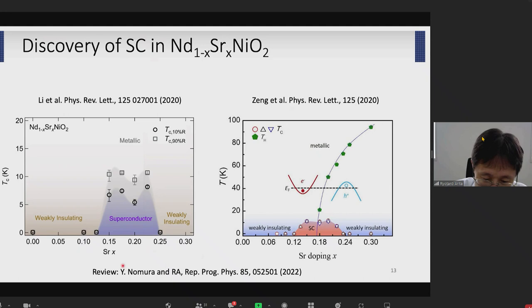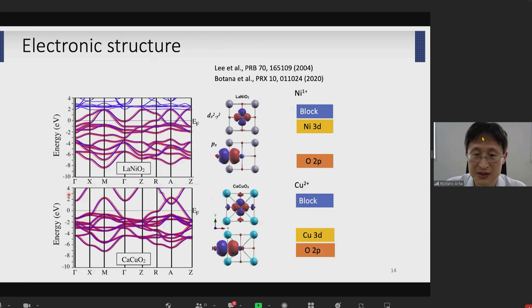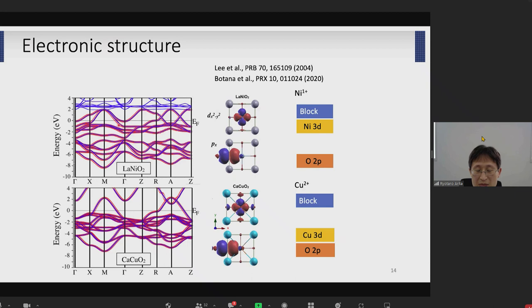This is the phase diagram — we see there is a superconducting phase. This material is now studied very extensively. Recently, Yusuke and I wrote a review paper on this material — please check it if you're interested. It is interesting to compare nickelate superconductors and high-TC cuprate superconductors. One common feature is that the nickel 3D dx²-y² or copper dx²-y² band makes a very large Fermi surface and is very two-dimensional — this band can be modeled by a tight-binding model on a square lattice.